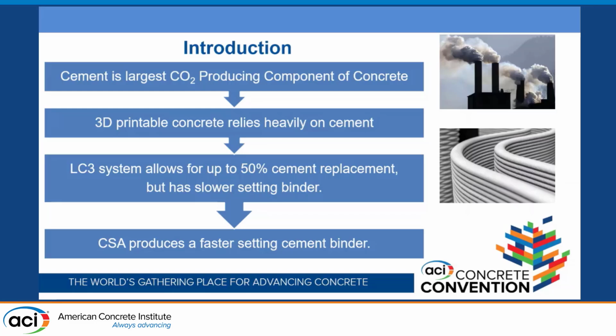So to counteract this fact, we explored the LC3 system, which would allow for up to 50% replacement of the cement content. So we looked at an Ohio-based clay, which showed comparable long-term, or 90-day, compressive strength or mechanical properties to PLC as our specific specimen type. But what we noticed was that at early age, for this specific type of clay, it actually has a slower setting binder. So if you think about 3D printable concrete and the supporting of the layering process, it's very important to control your early age rheology and setting time.